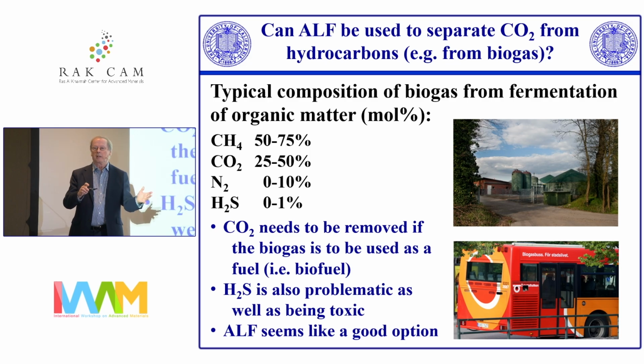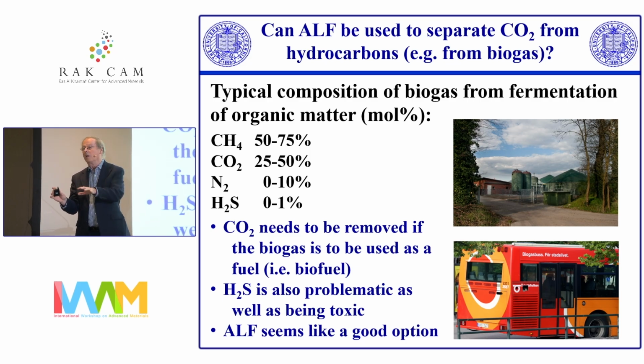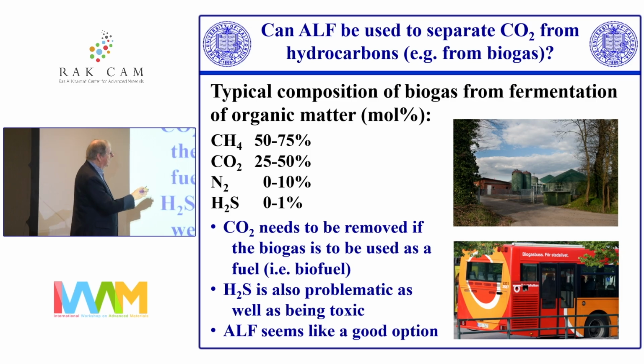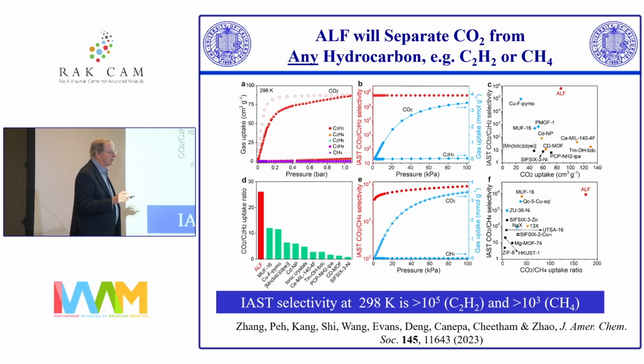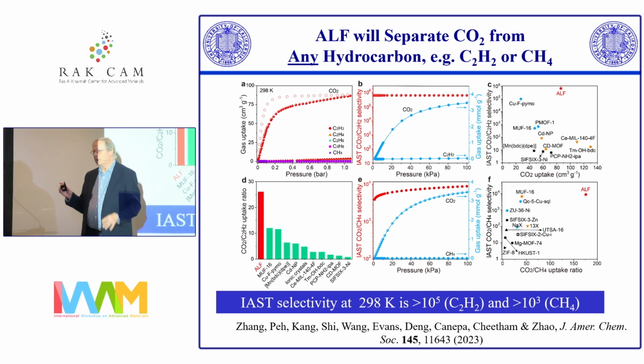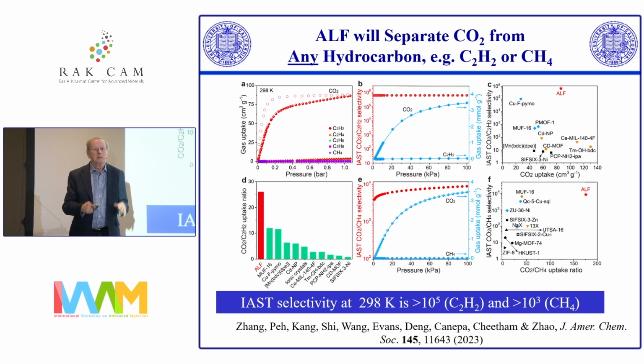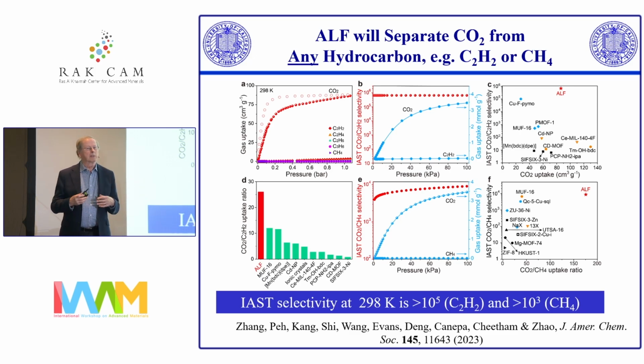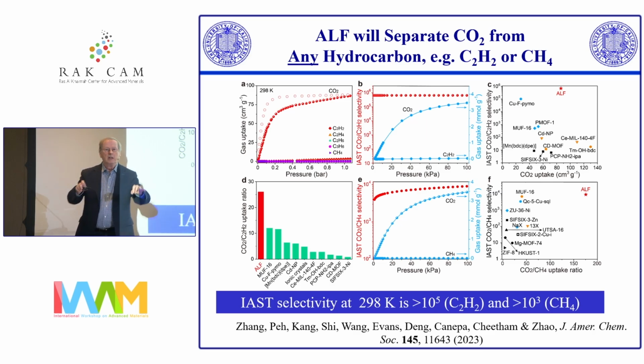And so we thought, well, can we separate, say, CO2 from the biogas so that the biogas is purer, primarily methane? And that works extremely well. And so what we discovered, and there's lots of data on here, what we basically discovered is that ALF will absorb CO2, but it won't absorb any hydrocarbon. Not only will it not absorb methane or ethane or ethylene, it won't even absorb acetylene. And so this kind of worried me because I thought we don't understand this very well, because acetylene is kind of thinner than CO2. So if this was all about size and, say, nitrogen being a bit bigger than CO2, so nitrogen won't go in.